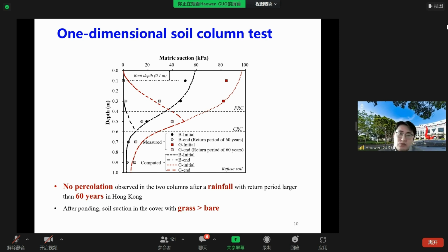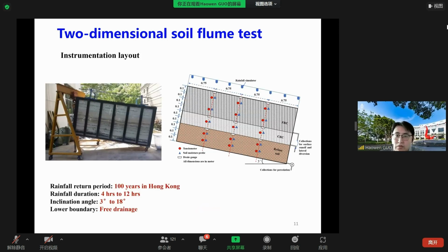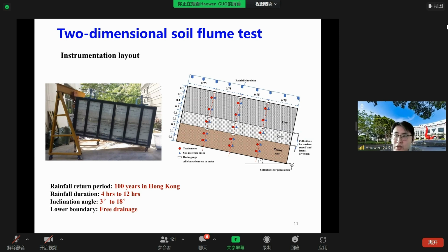Now the instrumentation of the flume model, from the right-hand figure. We can find that in order to simulate different rainfall conditions, a rainfall simulator was developed and installed above the cover system. By using this simulator, the rainfall intensity and duration can be regulated. In this study, the rainfall return period is fixed at 100 years in Hong Kong. The rainfall duration was changed from 4 hours to 12 hours. The inclination angle of the cover system was changed from 3 degrees to 18 degrees according to the national standards. Tensiometers and soil moisture probes were also installed in the flume. In this study, we mainly present the measured results in the middle section.